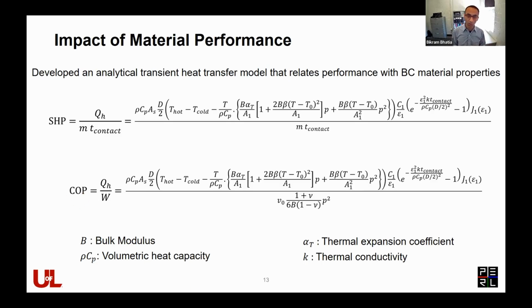Basically, we used the one-term approximation for transient heat conduction. So if we are operating at low enough frequencies and we can neglect the temperature gradients within the barocaloric core, we get these equations, which not only capture the material properties, so you can see the bulk modulus, the thermal expansion coefficient, thermal conductivity, and heat capacity, but at the same time, you also have device parameters such as the piston diameter, the surface area of that piston where the heat transfer is occurring, and also the hot and cold side temperatures. All of these are included in this set of equations that allow us to predict what the specific heating power and the COP of a device will be